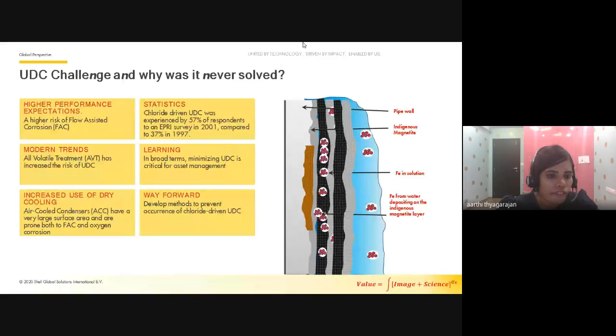Coming to the first point of high performance expectations, there is a continuous drive towards higher performance, and that will always lead to an increase in the velocities and hence generation of more ferrous ions and more magnetite particles that subsequently deposit on the evaporator tubes. At the same time, the maximum heat flux through the evaporator tubes has increased, which increases deposition rates, and hence the entire risk of UDC, or underdeposit corrosion, also increases.